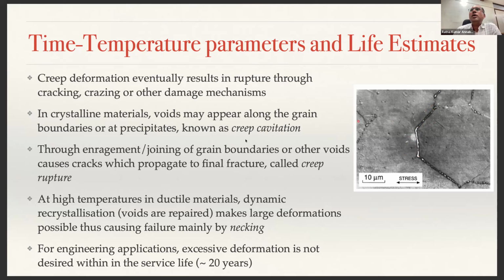And when these voids coalesce and form a larger crack, that is what we call final fracture or creep rupture. So in ductile materials at a very high temperature, you will have other mechanisms called dynamic recrystallization, because there will be diffusion of the material at very high temperature. Then there will be recrystallization of the material, and you will have large deformation without rupture because of the voids getting repaired and so on.